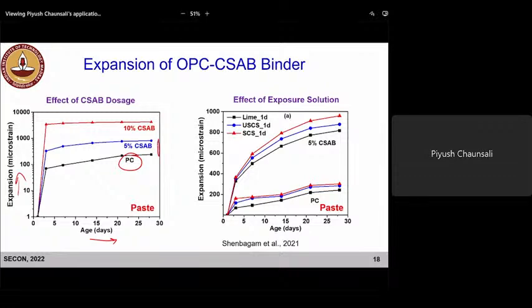But as we increase the amount of CSAB cement, so we are looking at the effect of CSAB doses, right? 5% addition led to an increase in the expansion, and at 10% you see a significant increase. A 10% addition of CSAB cement led to basically 3000 to 4000 microstrain of expansion. So an order of magnitude higher just by adding 10% CSAB cement. But we have also seen that it doesn't affect the strength. So we are maintaining our compressive strength, but we are making this cement expansive, which can be used to make it shrinkage compensating.